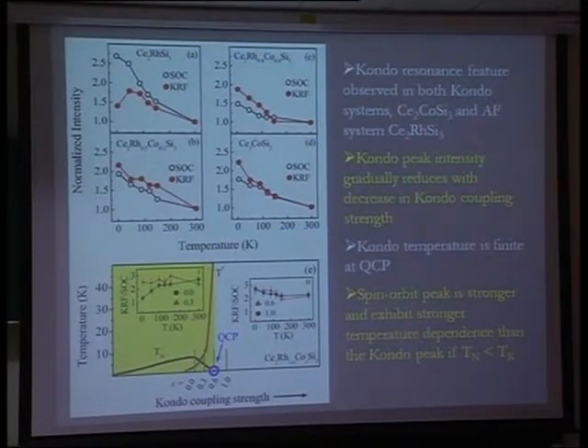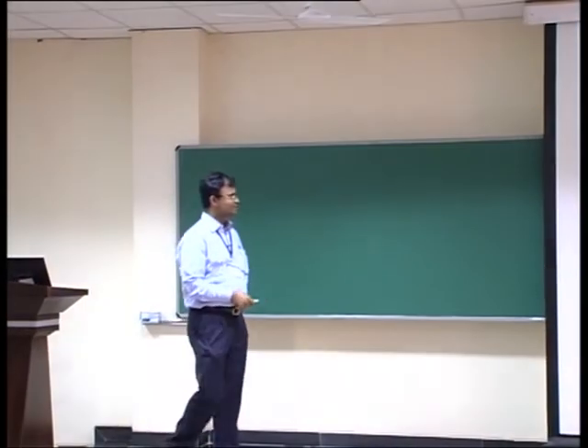If you are in the long range order regime, then you see that this Kondo resonance feature is weaker compared to this. But if you are in the strong coupling regime, then this peak is stronger than this. And if we plot the relative intensity, the KRF intensity divided by SOC, the spin-orbit peak, you can see that in this part of the phase diagram it goes up, because the Kondo resonance feature is dominant, but within this long range order phase it goes down. Okay. So what we find is that the spin density wave quantum criticality that people have been thinking about for so long can be found in systems of this kind.